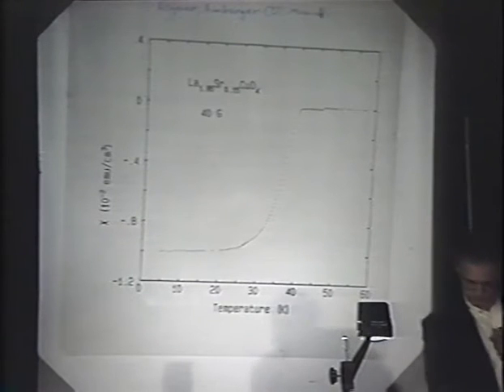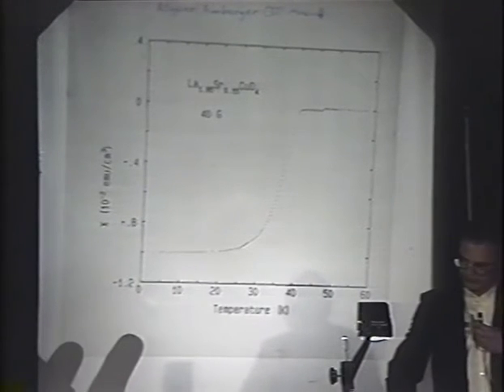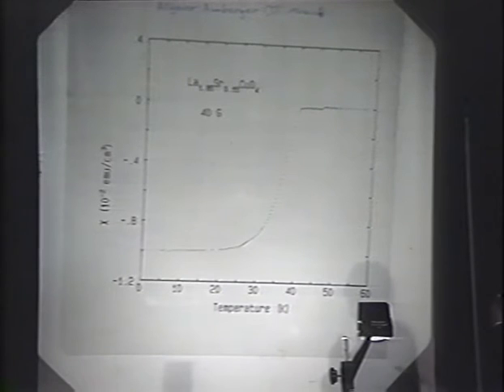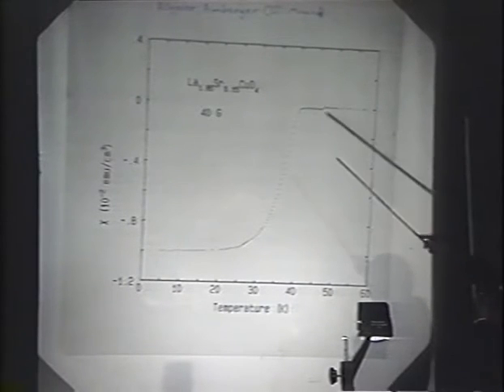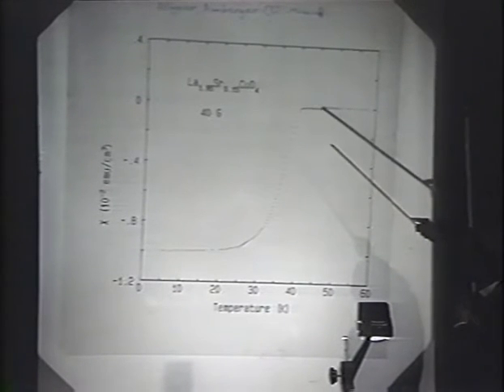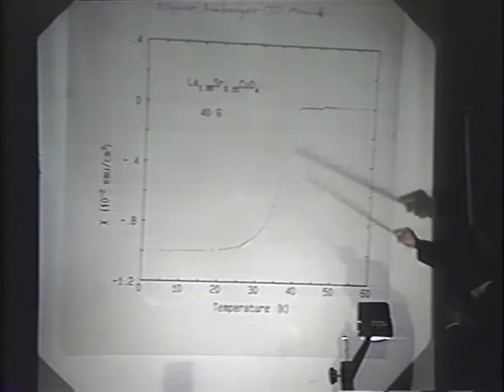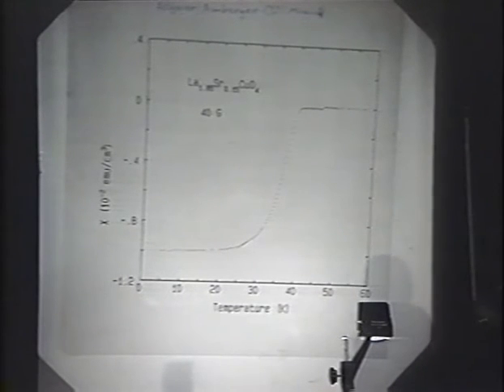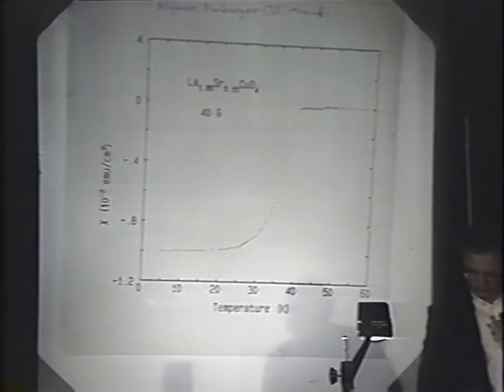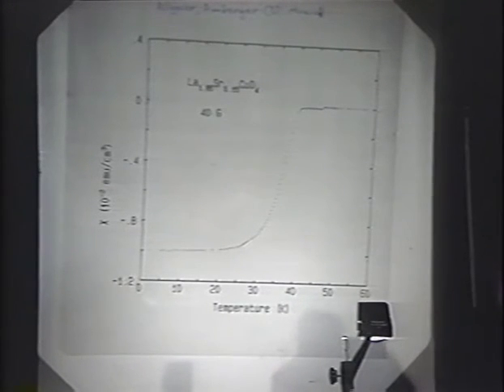We've also recently succeeded in making our own samples of this same compound, in collaboration with some chemists in Munich. This is an example of a measurement at 40 Gauss, a high-resolution susceptibility measurement versus temperature. One thing that might be interesting here is we observe in some samples a little drop at about 5 degrees above the TC, the Meissner effect, and this doesn't appear when you warm up again. We've seen this in a few samples, and I understand that some X-ray work has also reported similar results.